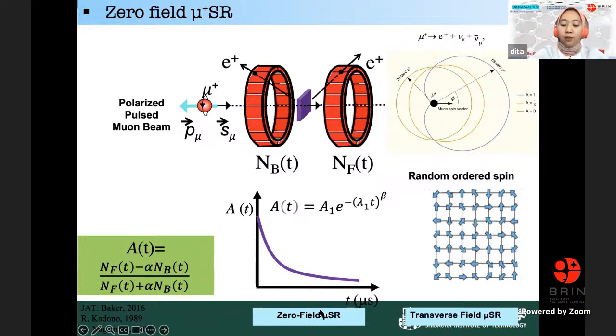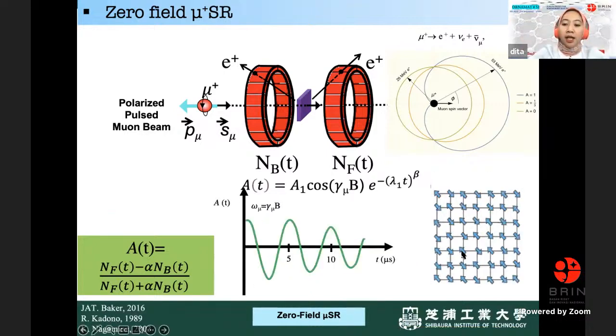So it's only zero field mu-SR. And if we have long range magnetic order like this, for example, this is antiferromagnetic up-down spin, we will see the muon will precess, and we will have the cosine function, without any external field. It's only from our sample. So the magnetic field is only from our sample because of the long range magnetic order. So that is the typical spectrum if you do the mu-SR experiment.